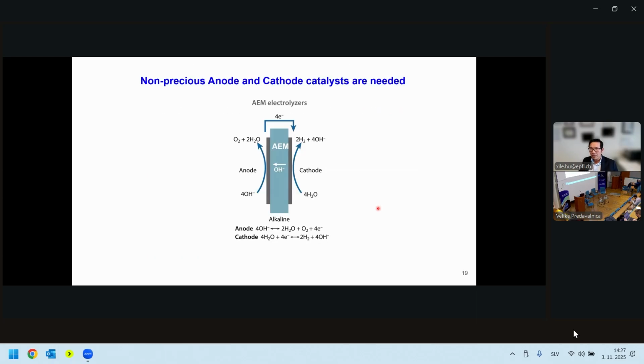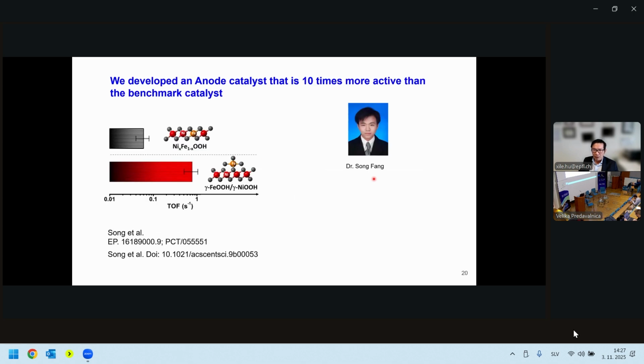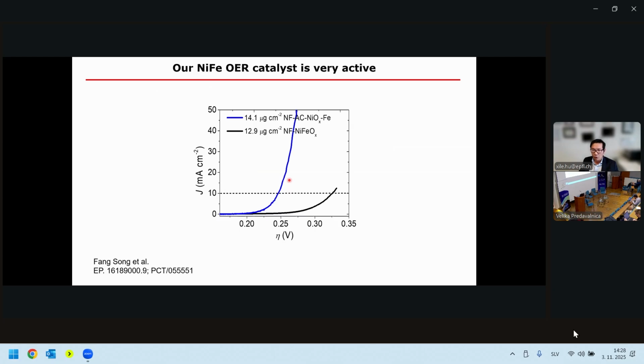Now we have the membrane, we also need other things. So we need catalysts, right? We need catalysts to make oxygen, we need catalysts to make hydrogen. And in our lab, from many years of research, we also have those compounds available. I just mentioned that we have a new type of anode catalyst that, from a turnover frequency point of view, is about 10 times the classic nickel iron oxyhydroxide. This was work by Dr. Song Fang. Compared with the classic nickel iron catalyst, we have a lower overpotential for similar current density, so we are much more active.